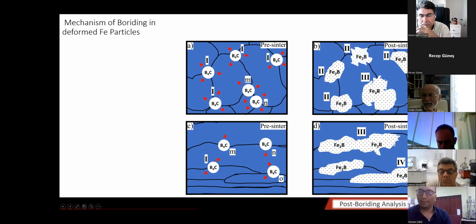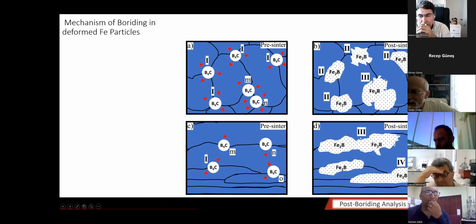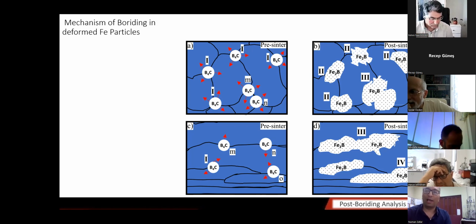Again, yes, sir. If I'm not wrong, it is shown on one of your graphics. After sintering, does the hardness decrease significantly? The hardness of the iron particles, or the hardness after iron sintering? After sintering, the hardness of the sheath decreases because of the recrystallization and coarse grains which are formed. But the hardness of the core increases because of the formation of iron boride phases.